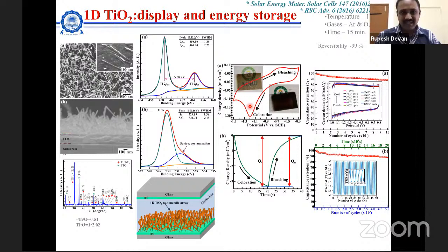Titanium dioxide is known to be a very good material for electrochromic smart windows, and it has shown very good properties for supercapacitors, with cyclic stability up to 10,000 cycles. There are very few materials which show cyclic stability up to 10,000 cycles for a supercapacitor. So this excited us. What if we put these two one-dimensional materials together for field emission displays?